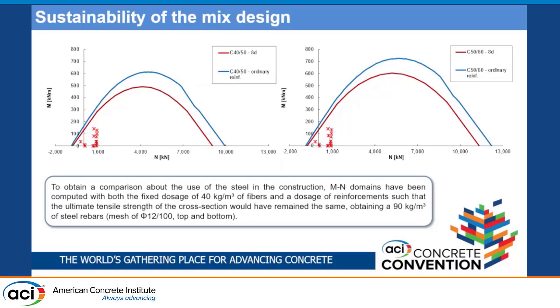So how did I find the 90 kg per cubic meter? We have assumed that the equivalent solution with steel reinforcements has to have the same ultimate limit tensile strength. So doing the computation, we have seen that we have to put a mesh of 12 millimeters, step of 10 centimeters, top and bottom of the cross section.